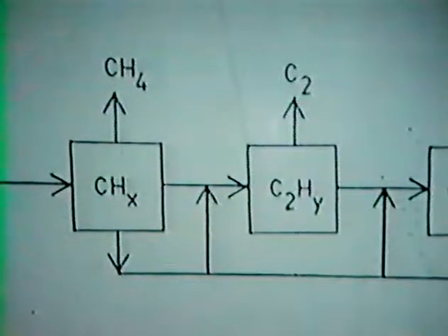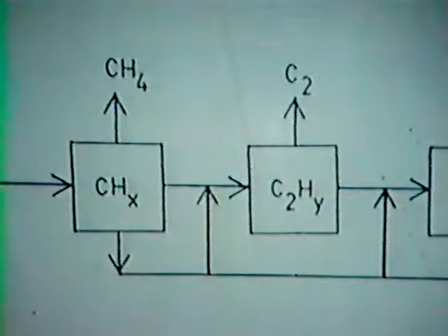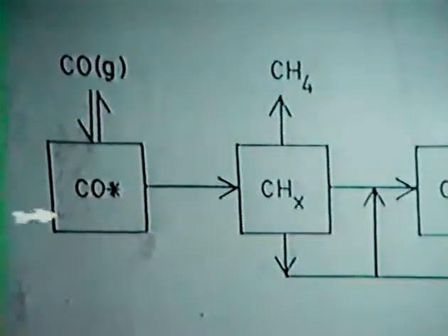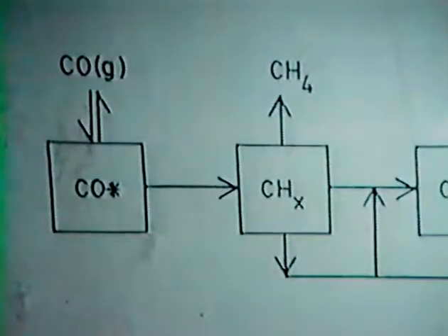We've measured these. The surface is about 2/3 covered with CO and 1/4 or so covered with CHX fragments.